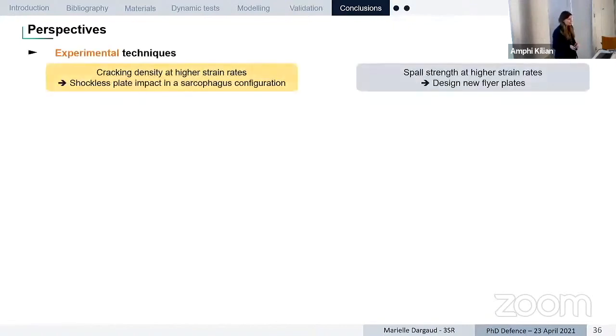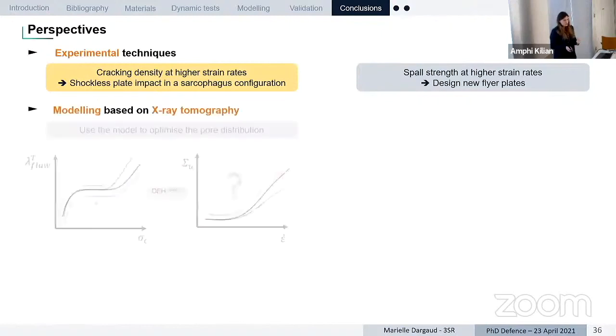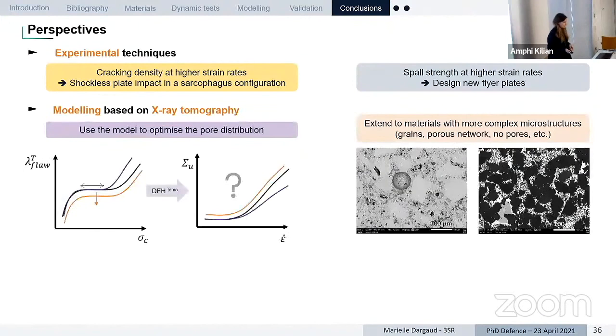There are main perspectives for this work. So first, for the experimental part, we would need to try to reach higher strain rates. To do this, we could use the shockless plate impact, but in samples in a sarcophagus configuration, and design new flyer plates to reach higher levels of strain rate. For the modeling part, now that we've seen that we can have an explicit continuous description of the flaw population, we can now play on the shape of this continuous flaw distribution that we can decide and see what is, from the DFH model, the output, and how to improve the strength of the material this way.